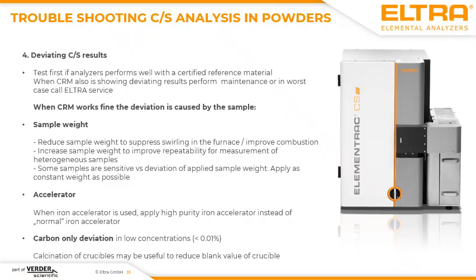When you only have, I would say, deviating carbon results, and these carbon results are measured in a very low concentration range, really below 0.01%, make sure that the crucibles you are using are calcinated, which does mean they are preheated at 1000 degrees at minimum for 1 hour. This would reduce the blank value of the crucible.